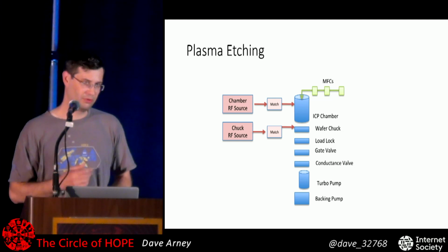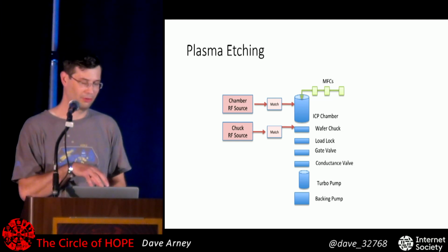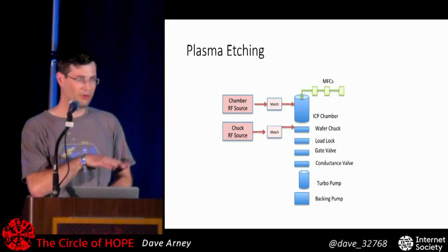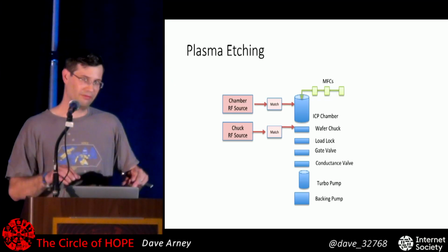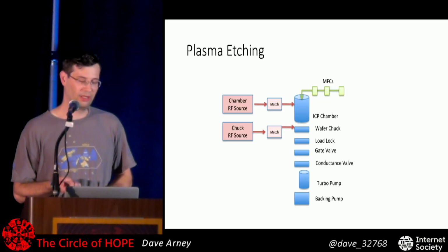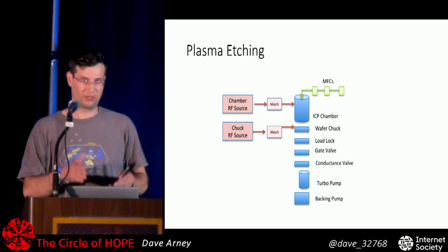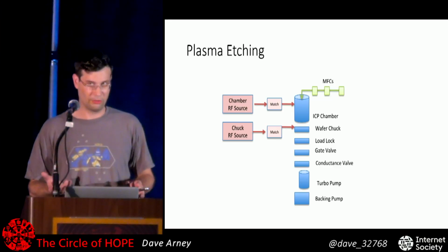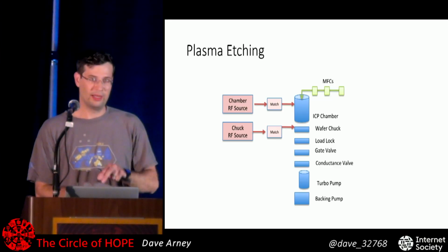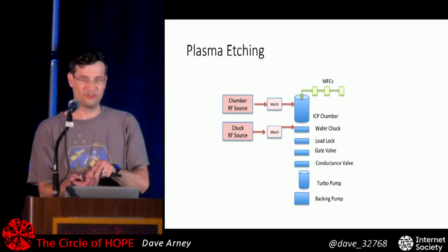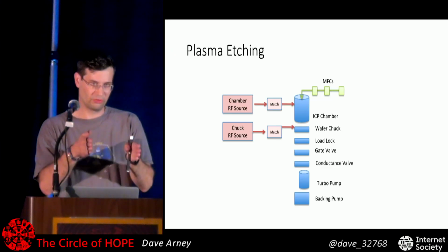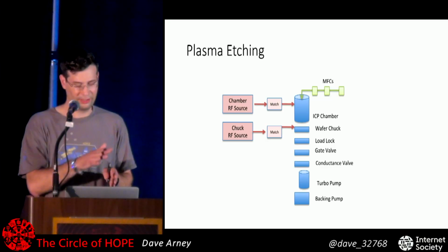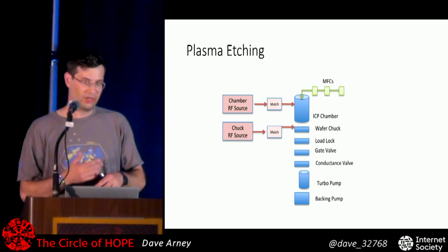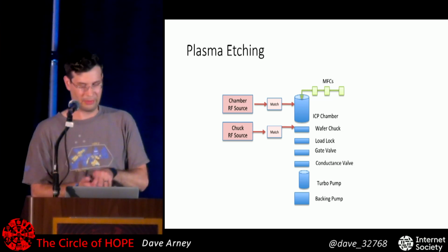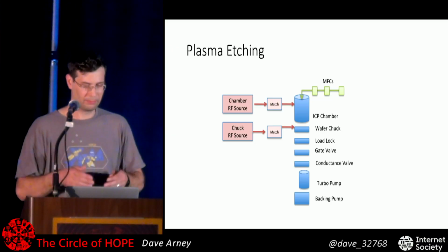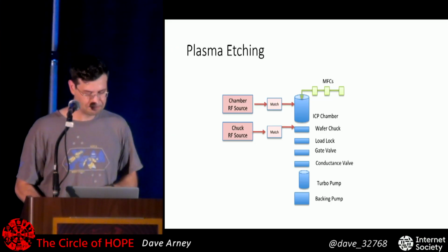And so you alternate. You do a round of bombarding with chemicals that are going to etch the silicon, and then you bombard it with a little bit more mask. You apply a very thin, not very strong layer of a mask to the entire thing, and that's going to coat the sides of the channels, it gets the bottom, it goes over the top, it kind of goes everywhere. But that gets eaten away on the bottom of your channel very quickly when you start to etch again. It's not very strong, but it's strong enough to mostly resist the few ions that are hitting the sides. And so by alternating masking and bombarding, you eat away at the bottom of your channels but keep the sides protected.